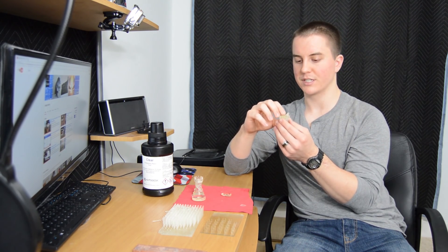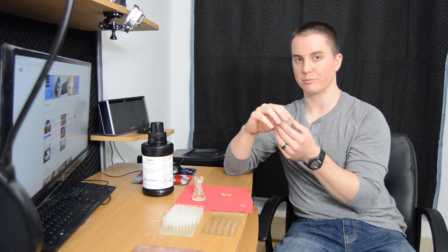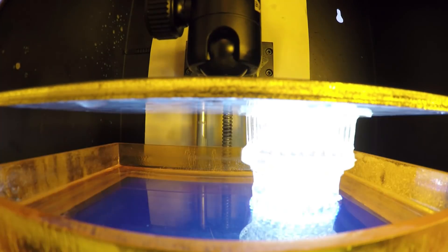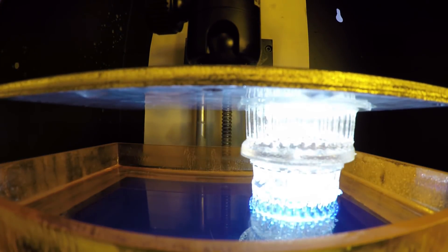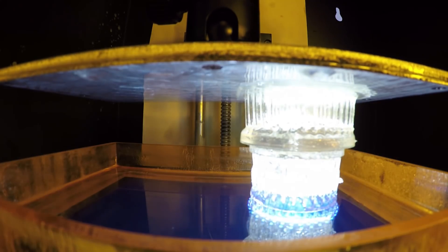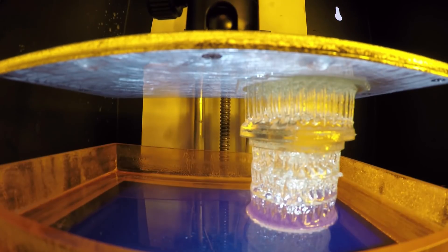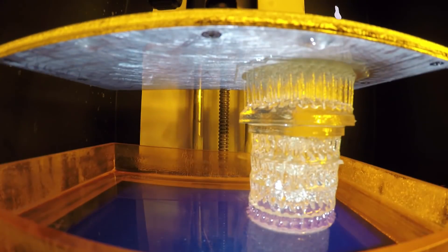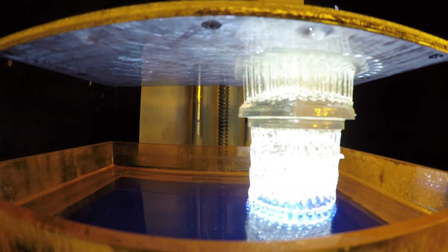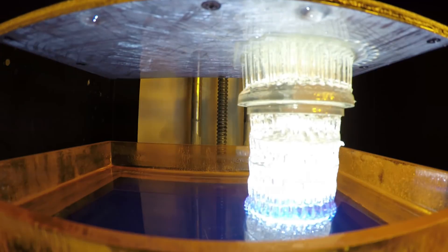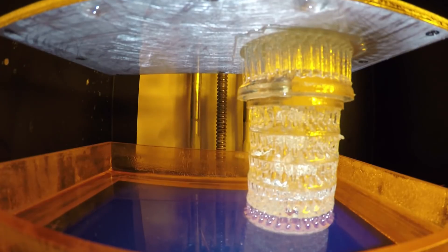I made the mistake of trying to do a pretty large print and ran it overnight. I filled up the resin tank with about as much resin as it would hold, but because of that, a lot of resin gathered up on the part as it was printing, and that light being projected through the part just cured all that excess resin.